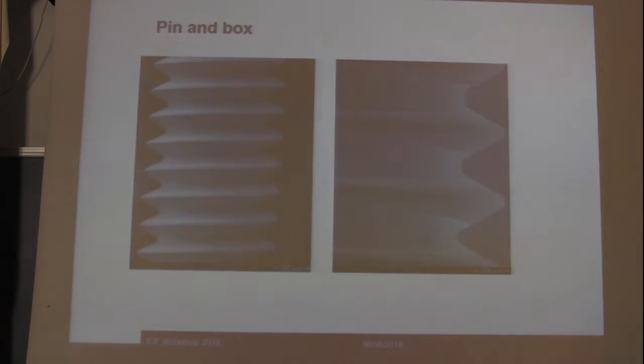Another important test is to evaluate the machinability of the alloy. You can see on the left a detail of a screw. We produced the screw using the overaged alloy, and as you can see, the surface of the pin is even, and you cannot see cracks or irregularities on the surface. On the right, you can see a SEM micrograph showing the box, the female thread. In this case, we obtained that on the alloy aged for 14 hours. Even in this case, you can see that there are no cracks or irregularities on the surface.